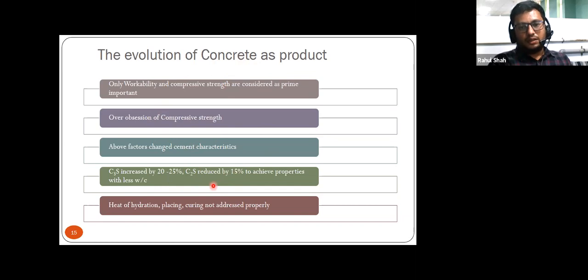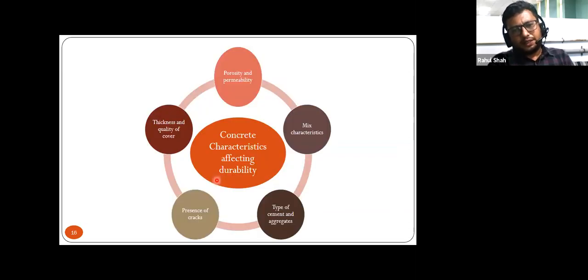The process of initial setting time, the early strength hydration, formation of secondary products in cement phase is also not handled properly. So in a nutshell, suppose we want to say which are the factors which affect the durability, right? So first and foremost is porosity and permeability, right? Because when concrete is more porous and more permeable, there are chances that concrete will attract more water to it. There may be the chances of corrosion in the concrete. So if concrete is more porous, even though you have used excellent material, it all goes in vain.